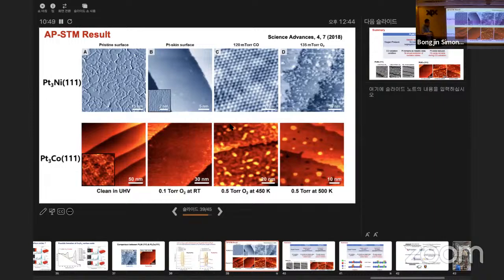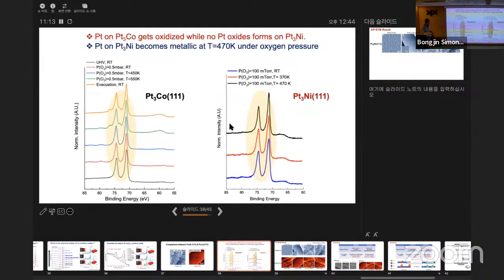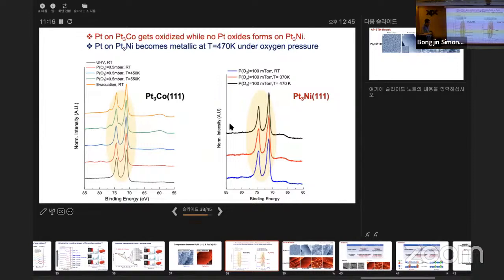And by the time you increase the temperature a little further, you see this more, big islands of this. But of course, we introduced a little bit more temperature than room temperature. But the oxide that is being formed on the surface is bigger, stronger, and so these are the differences. And we think that because of this, with platinum cobalt you form this, you can see this oxidation of the platinum. Platinum nickel, you don't see it.